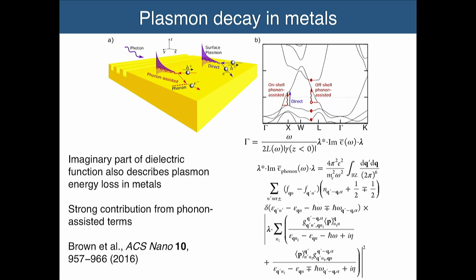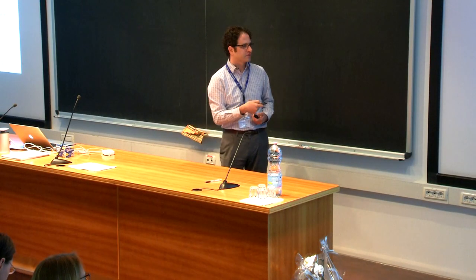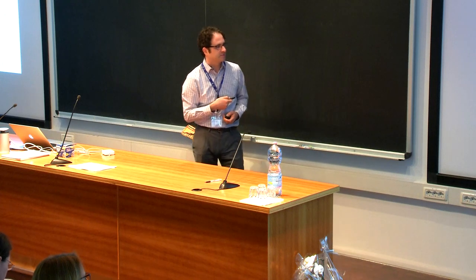The dissipation rate is directly proportional to the imaginary part of the dielectric function. And again, there is a strong phonon contribution. So you see here similar equations to the ones that matter for phonon-assisted optics. And they do contribute a lot for metals, because as you can imagine, when you go to long wavelengths, you primarily have the phonons contributing to this absorption. So the details come from this manuscript.